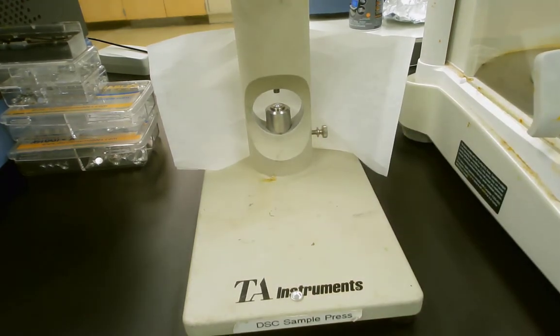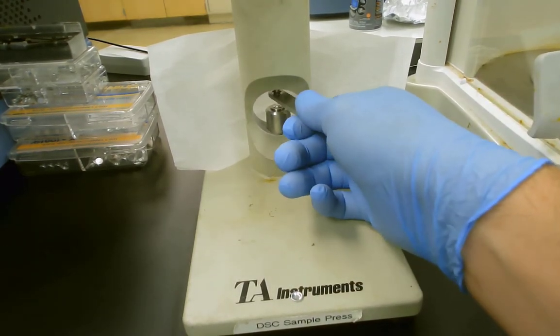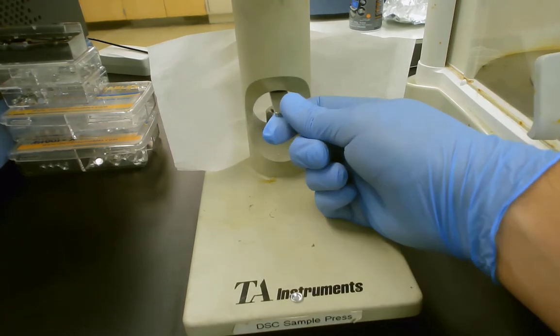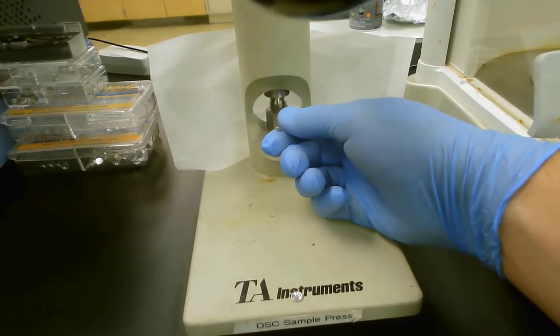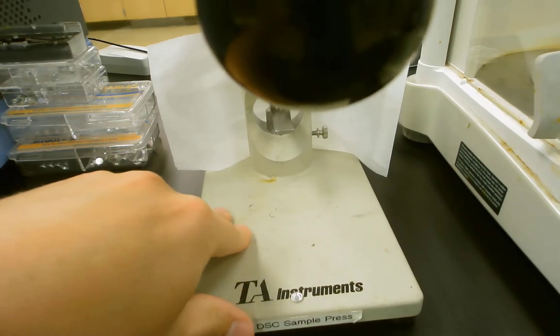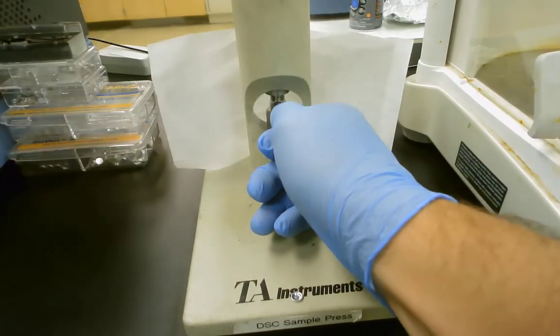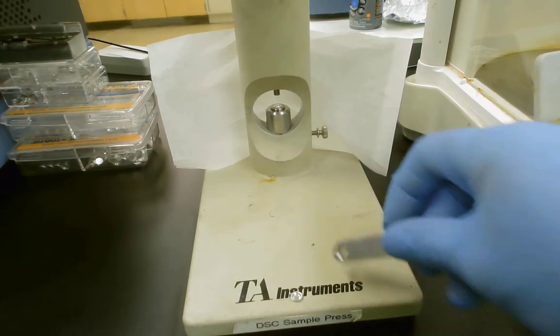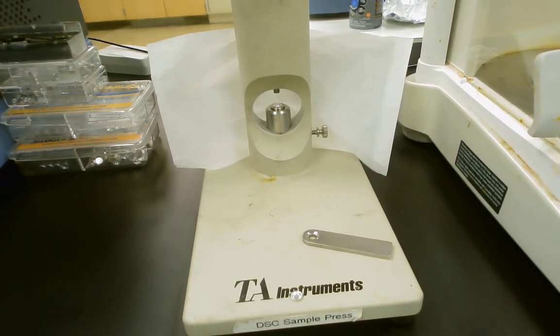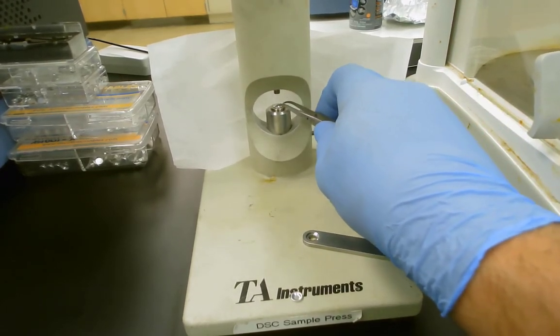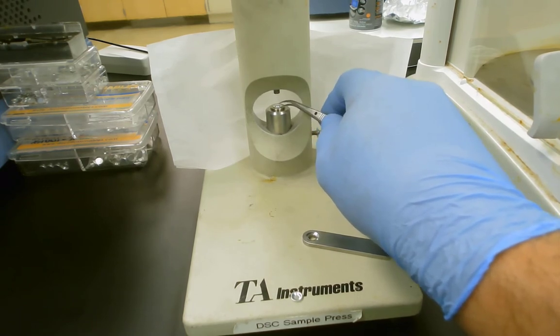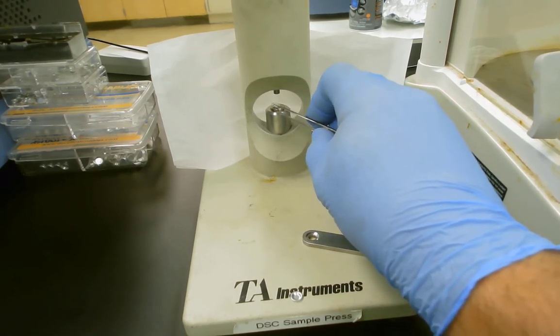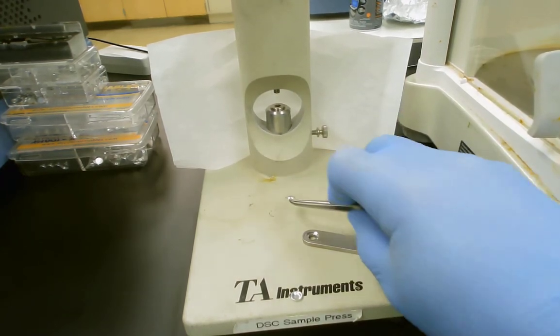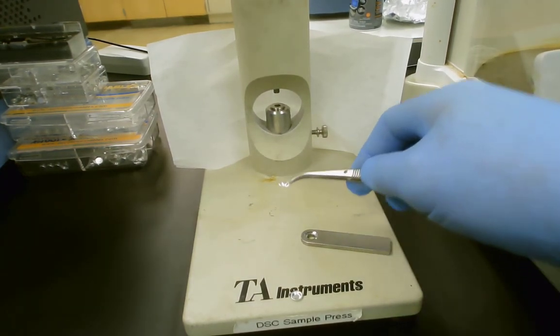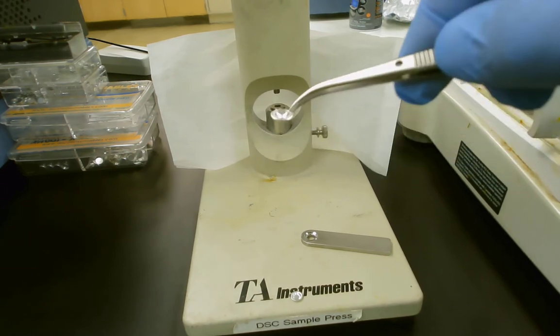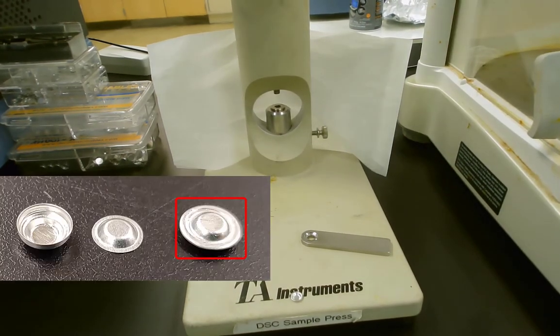And then again, the edges of the pan have been bent in just a bit. And so then the next step would be to use the flat side to make sure that the edges of the pan are fully bent in. Because this is such thin aluminum, you don't want to press down very hard. It is possible to break the seal by thinning out the aluminum too much. So there we have our first crimped sample.